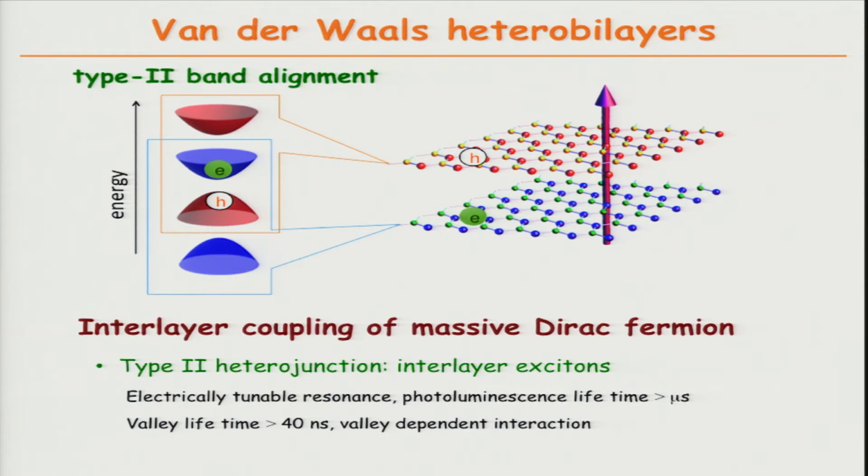So in this case, the excitons would have the so-called interlayer configuration because electron and hole would have low energy in separate layers. And those interlayer excitons have been found with appealing properties, with very long lifetime but still bright, so that you can observe them using photoluminescence. And the lifetime is very long because the major mechanism for the valley depolarization has been quenched in this interlayer configuration.